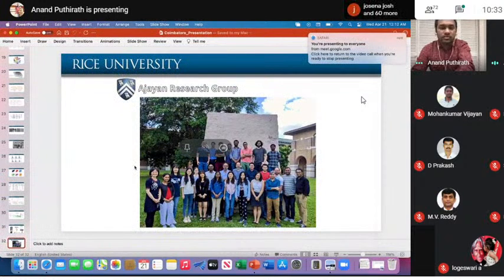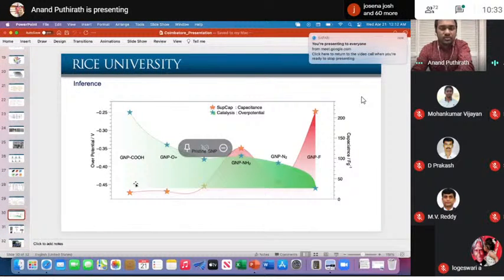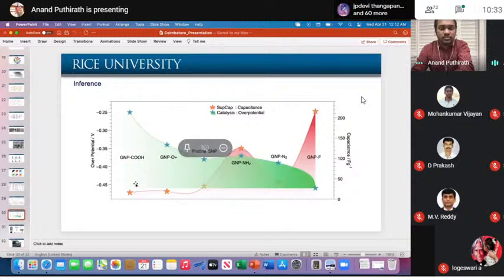I have one question. For graphene, the stability of the monolayer is not that much of an issue if you compare it with some MXenes or several TMDs. So how does that affect things? For example, MoS2 monolayer is stable for only a few hours. Then you can think that black phosphorus is stable for only a few seconds or a few minutes in the monolayer form. Actually, when we come to the 2D confinement regime, there are different phases, right?